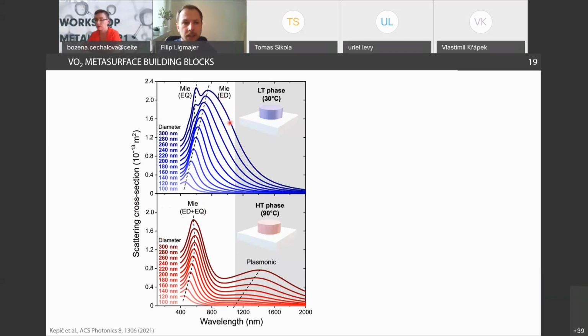So we investigated metasurface building blocks made of VO2, which is nanostructured into the form of nanodisks. And here you can see calculated scattering cross-sections. This is a very important metric for metasurfaces, because you want a large scattering cross-section in order to influence the light which hits your metasurface.